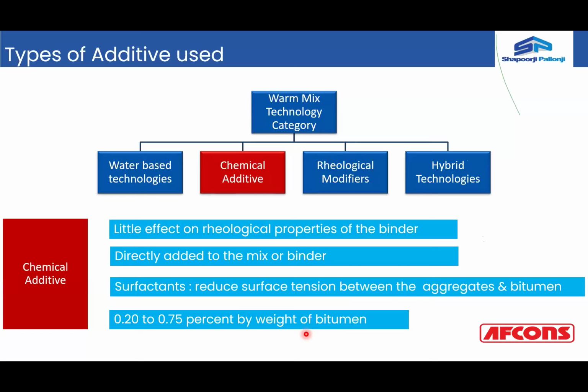And of course, you can reduce your rolling efforts by 2 to 3 passes as compared to the conventional rolling methods. Generally, when you talk of the conventional rolling of hot mix asphalt, you go with a plain pass first, followed by 3 vibrations, low, medium, and high, or high, medium, low, depending upon the trial patch and the aggregate types. And then again a plain pass, followed by PTR and a plain pass.